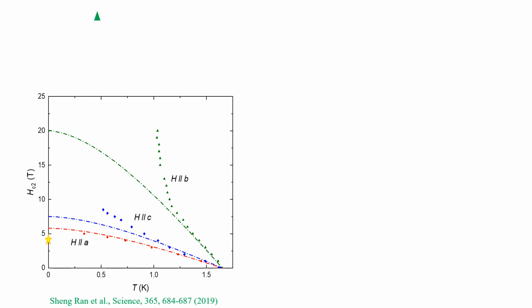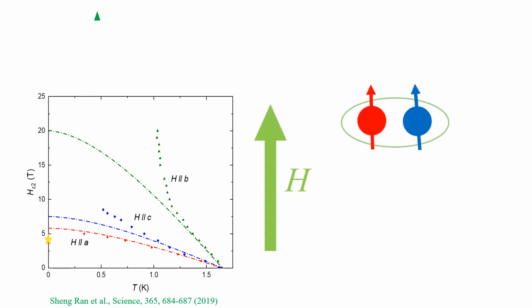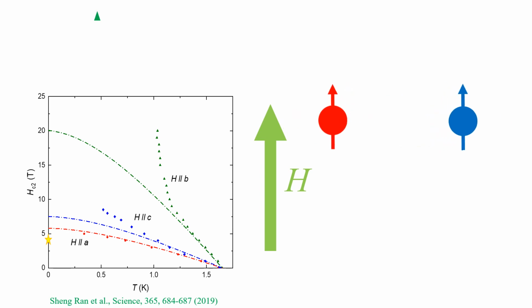There can be a very simple explanation for this extremely high critical field. As I mentioned earlier, for a spin-singlet pairing, the magnetic field wants to flip one of the spins and then break the Cooper pair. But if it was already a triplet pairing, the spins are already in the same direction. Magnetic field would not break a Cooper pair through this mechanism. So this result strongly indicates we actually found a spin triplet superconductor.